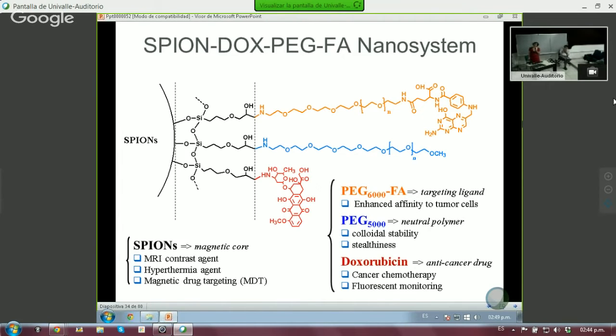Okay, so now if we go back to our cooking, what do we have here? We have the SPIONs, and then we have to dress them up. So what we start doing is we put, first of all, the PEG, which is the polymer, 6,000, and this PEG is highly biocompatible. And we add to it something called folic acid. As you can see, this folic acid is represented in this orange color, and I'll get back to why we use folic acid. And then we also used some PEG 5000, and this is a neutral polymer.